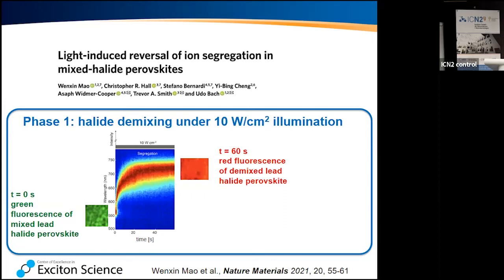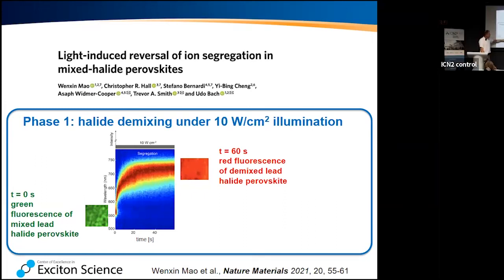So here, that's a similar image to what I just showed you. We're starting off with a green fluorescence. Green is from the fully mixed phase. And then we shine light on it, 10 watts per square centimeter for about a minute. And we end up in a fully phase segregated material. That's what everybody would expect.